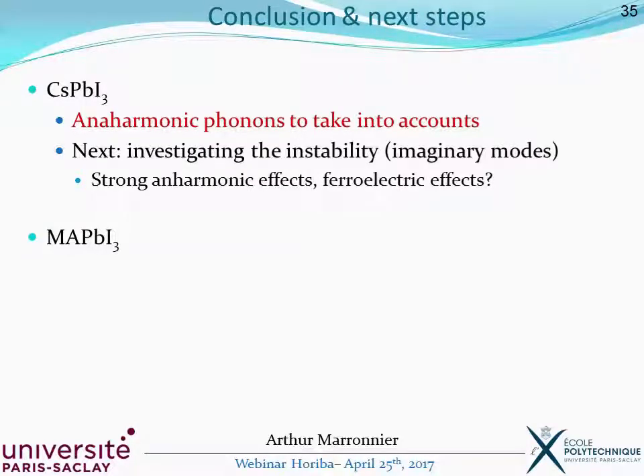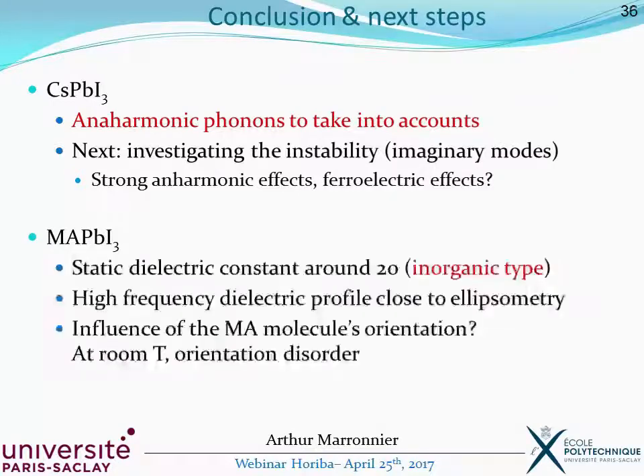But in the hybrid perovskite, MAPbI3, we didn't find any structural instabilities. We found a dielectric constant around 20, which means that it behaves like an inorganic type semiconductor. We have a good match in the high frequency regime between ellipsometry measurements and our calculations. And one last point is that we haven't here in the calculations taken into account the influence of the organic molecule's orientation, and it has been reported that at room temperature you could have orientation disorder due to this movement. So this could be a next step also.